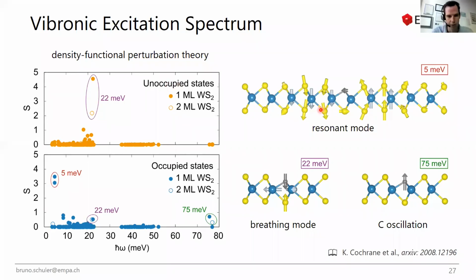It could reproduce which phonon modes are mainly contributing, especially these breathing type modes, which involve the carbon, the opposing sulfur, and the tungsten neighbors. But also then the carbon oscillation, which is at higher energy, on the order of 70 to 80 milli-electron volts. And this is especially important for the occupied states. We don't see it for the unoccupied ones, which is also consistent with the calculations. And there is also this resonant mode, a more delocalized mode, which is more important for the occupied states.